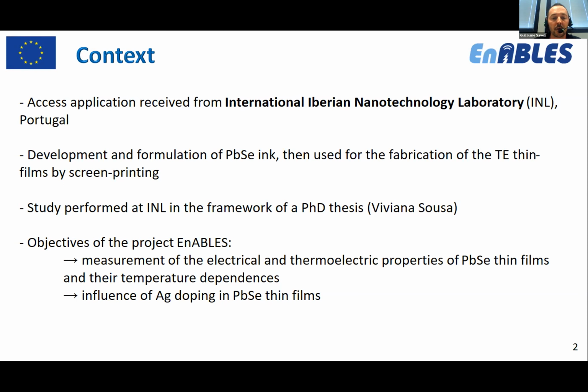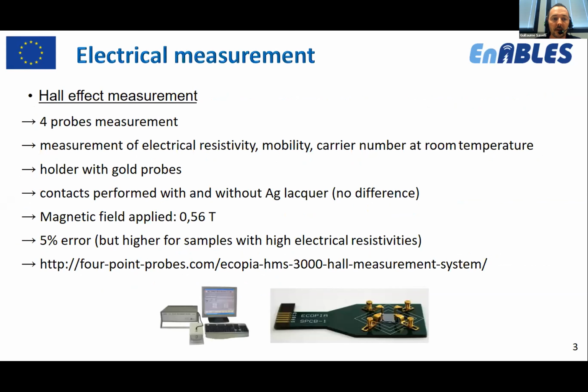Here at CEA Liten, we have a lot of characterization tools for thermoelectric applications, both for materials and devices. That's why they contacted us to help them characterize their materials. For the electrical property measurement, we use Hall effect measurement, which is a 4-probe measurement, as you can see in the pictures below. So we can measure the electrical resistivity, mobility, and the carrier number at room temperature. For that, we use a holder with gold probes, as you can see here.